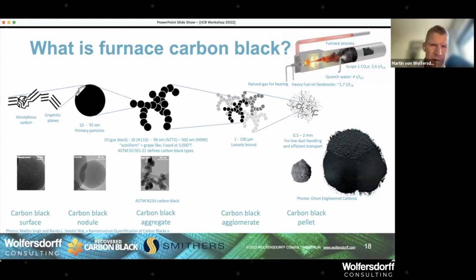And we need about 2 tons of oil for 1 ton of carbon black. Here, okay, it's more precise, 1.7 ton. That really depends on the type of carbon black we want to produce. But we need a lot more feedstock than carbon black. And then these little primary particles, they grow because the oil droplets bump into each other. And so the particle size is increasing as the gas is traveling alongside the reactor.